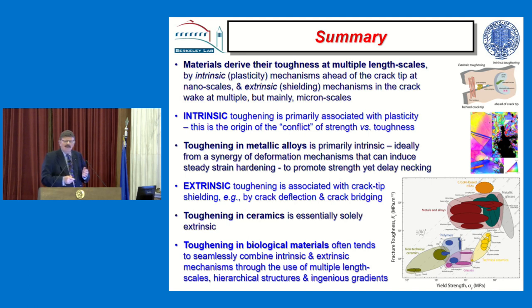I've talked about this notion of intrinsic versus extrinsic toughening. Intrinsic, due to plasticity, ahead of the crack tip, generally from ductile materials. Extrinsic toughening, nothing to do with plasticity, all to do with shielding of the crack by mechanisms like bridging and deflection. The intrinsic toughening mechanisms really are the ones that are generated in these new high entropy alloys, which are remarkably tough because they can generate that. The extrinsic toughening pertains to ceramics, where you can't have much plasticity. And they're the ones that have allowed us to make these ceramic composites now, which are going to be used in gas turbine engines. It's interesting.